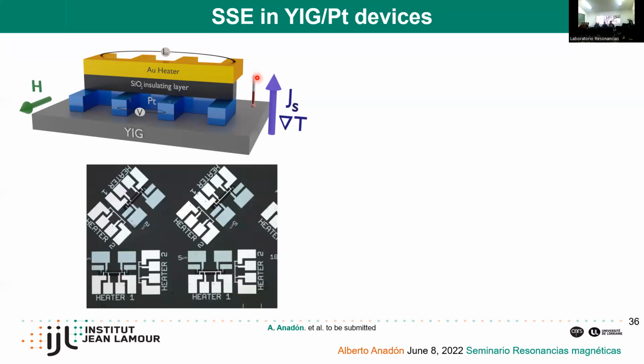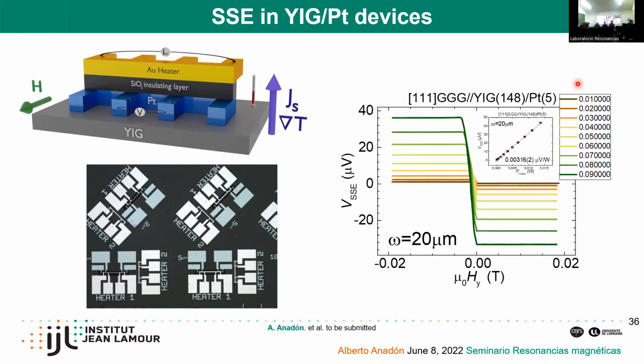And this is how the devices look when we look at them at the microscope. Basically, here we have our heater, here we have our sample. This small square here is the silicon oxide in between both terminals. And if we apply a current in this heater, we are heating in the out of plane direction, and we will observe this kind of curves when we change the power. So each of these loops is a different power, which then the saturation voltage, as expected, increases linearly with the power that we are introducing in the system. So this is a good indication.